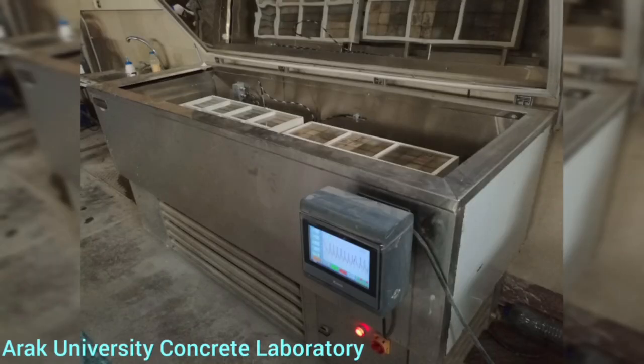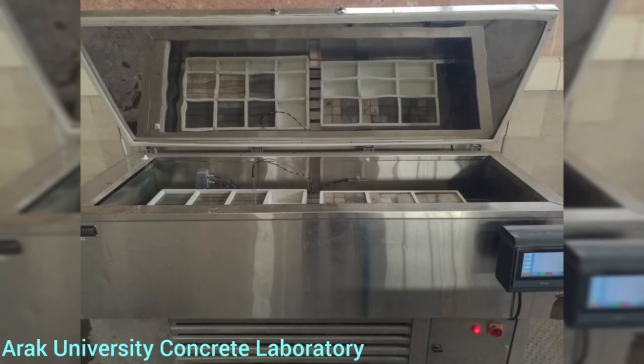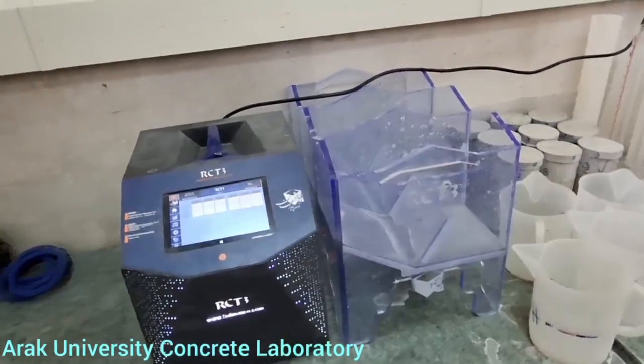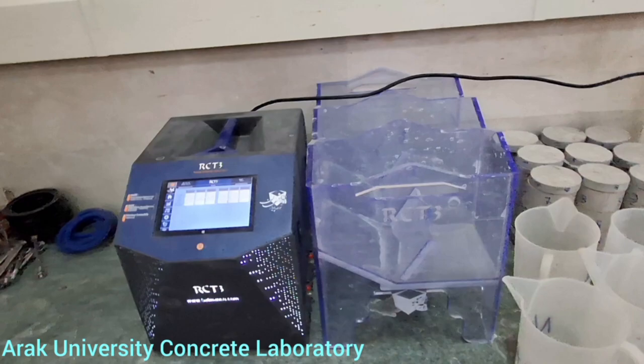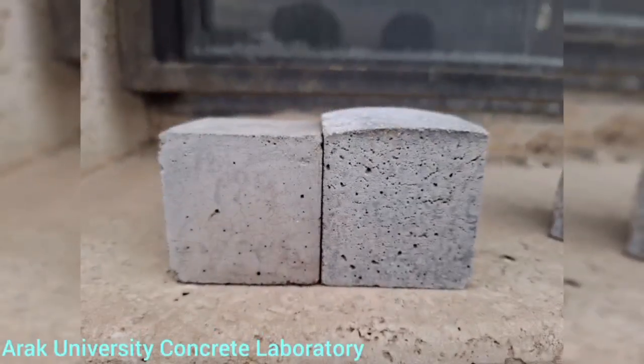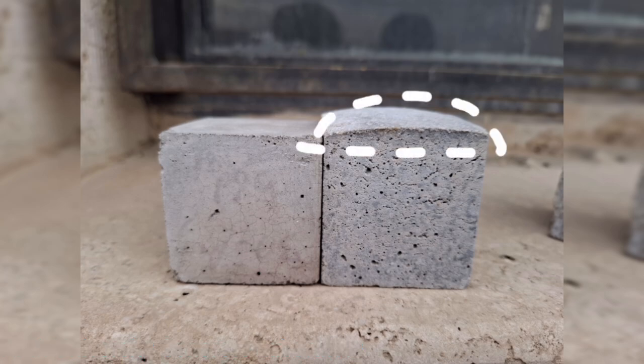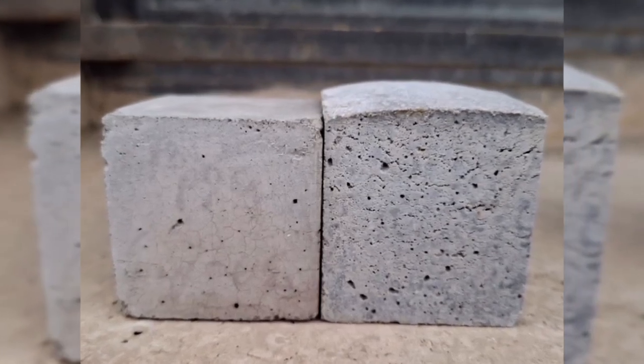Durability tests are then performed. Concrete samples are subjected to freeze-thaw cycles to evaluate performance under harsh conditions. Chloride permeability is measured using RCPT to assess resistance against corrosive agents. Here, concrete containing dross on the right is compared with ordinary concrete on the left. Its appearance resembles a puffed cake, with gaps forming between particles due to reactions between aluminum particles and moisture, and it shows more pores and is more porous.